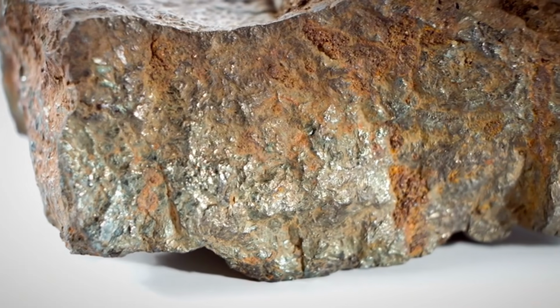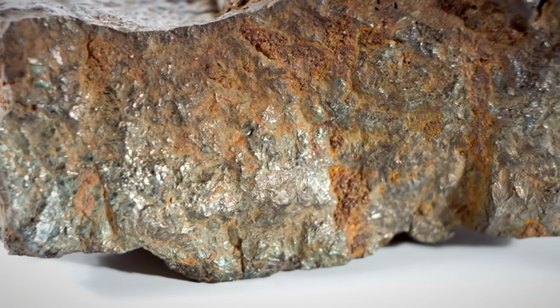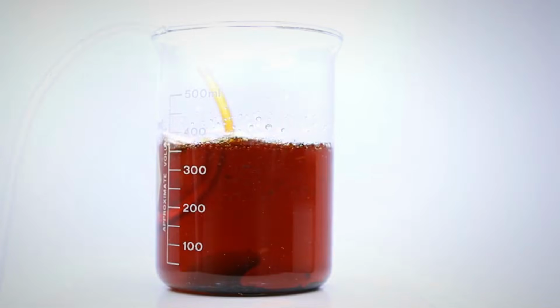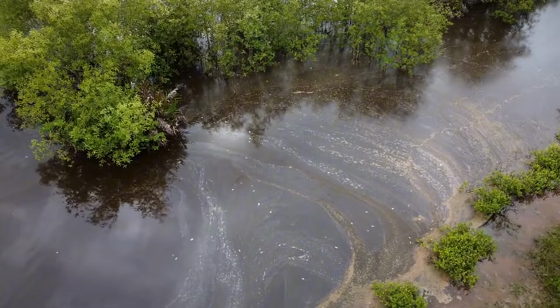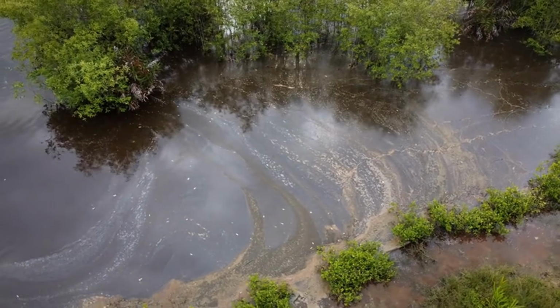We're now at the micrometer scale, fine enough for gravity tables, flotation, or chemical leaching. At this level, you're no longer dealing with rock in any practical sense. It's now a homogeneous feedstock for recovery, and how you process it depends on the type of gold present. It's worth noting that not all ores respond the same way. Free milling gold, which separates easily once crushed, is ideal. But sulfide-hosted or refractory gold, locked in pyrite or arsenopyrite, requires chemical liberation.